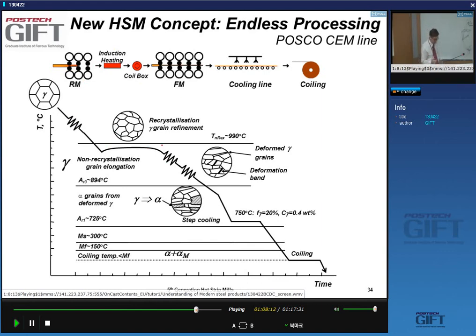Then say you're making an HSLA steel, yes? The material will contain niobium additions, etc., so that you have a temperature of non-recrystallization and a zone of non-recrystallization, yes, in which you do the finishing rolling, right? So in this case, you get deformed gamma grains with deformation bands and lots of dislocations, so that when you go through the transformation in the cooling line, yes, the alpha grains are formed in strained or deformed gamma.